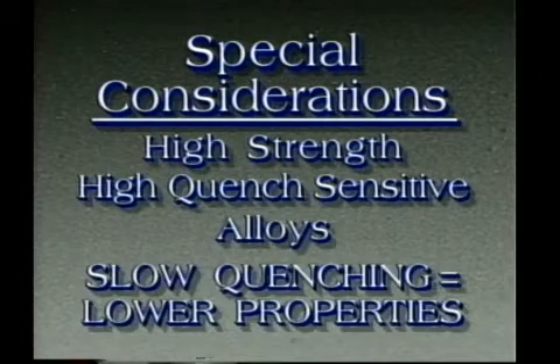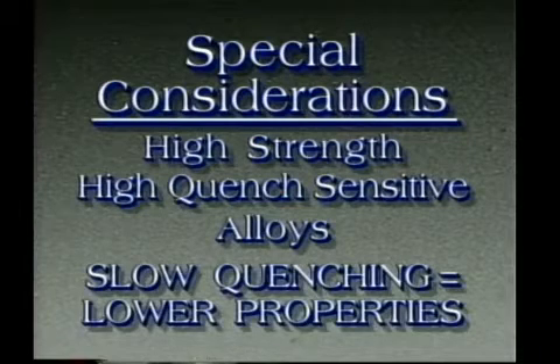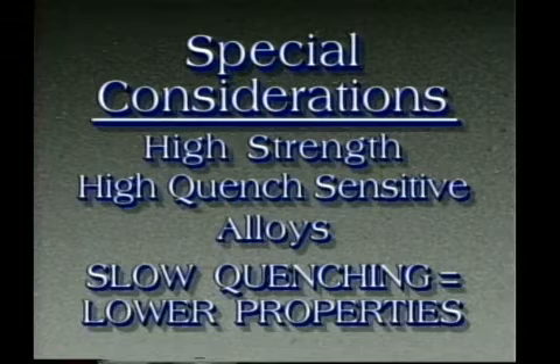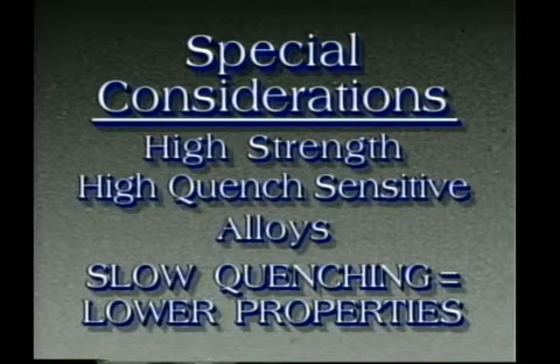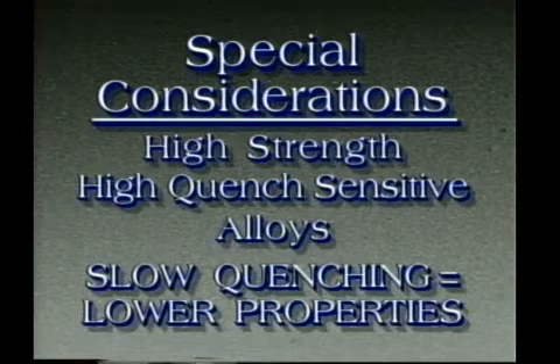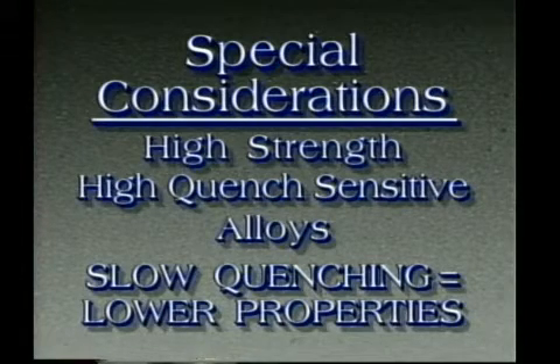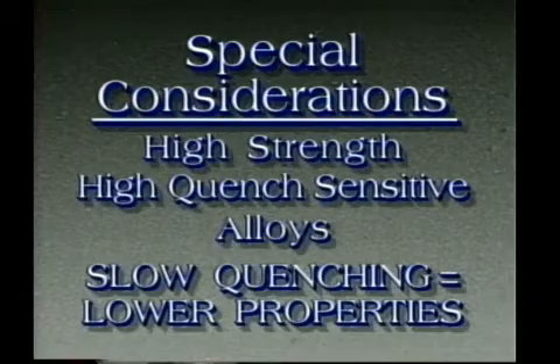Most higher strength, highly quench-sensitive alloys, such as 7075 and 2024, are not spray quenched, except in special circumstances, because slower quenching can result not only in lower properties, but also a significant reduction in intergranular corrosion resistance. If a spray quench is used on these alloys, it must be a heavy volume spray, which floods the part rapidly, and it must extract a large amount of heat quickly. A light fog or mist spray or quenching with a handheld hose is not adequate for quench-sensitive alloys and for the thicker parts of even the less quench-sensitive alloys.